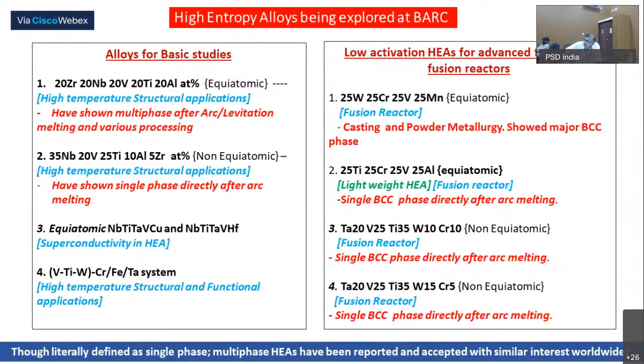The idea is 20 zirconium, 20 niobium, 20 vanadium, 20 titanium, and 20 equiatomic ratio, and you get the highest entropy of 1.5. Why we are doing it is zirconium and titanium form the same group of element, group 4 element. Vanadium and niobium form group 5 elements. These all 4 elements show the phase separation tendency. They have shown the segregation tendency, that if you put them in the alloy system, zirconium atoms try to segregate, niobium tries to segregate in another place.